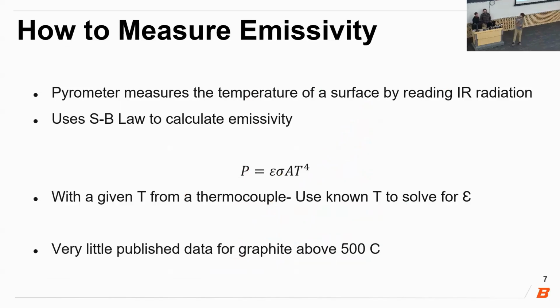So how do we measure this emissivity? We use a pyrometer, which takes infrared radiation from a surface, and using a known temperature from a thermocouple, we can use the Stefan-Boltzmann law to backtrack for emissivity. Why are we doing this? Well, there's not very much published data on the emissivity of graphite above 500 degrees C, and modern reactor designs are having operation temperatures above 500.